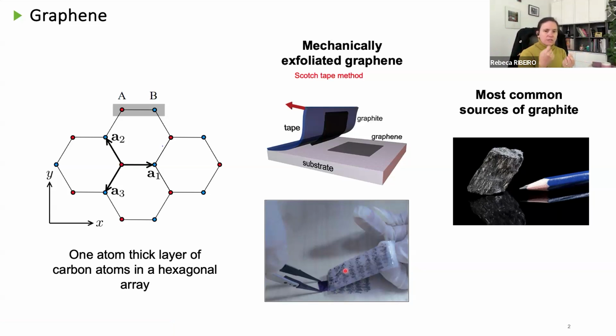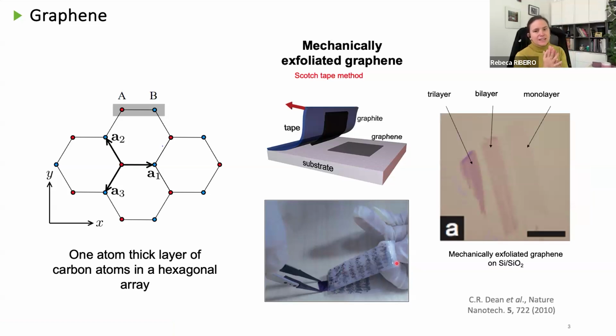You need a very specific substrate to be able to observe graphene, which is silicon oxide of a very precise thickness. There are two thicknesses that are most used, 90 nanometer silicon oxide and 300 nanometer silicon oxide. You were wondering, why do we need this? Well, as you can see in this picture, graphene, okay, there it is. Graphene is very transparent. In fact, it only absorbs 2% of the light, and then it becomes very difficult to find it optically. But this also makes it very attractive to make transparent electronics.